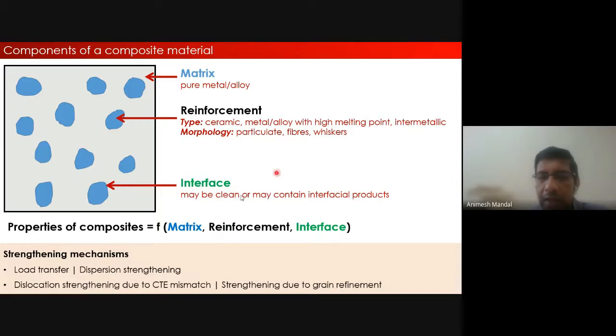So the interface plays a very, very important role apart from the matrix and the reinforcement. What we can summarize is that the properties of these composites are a strong function of not only the major phase and the minor phase, that is the reinforcement, but the interface also plays a very important role in dictating the properties. If you are aware of the several strengthening mechanisms which we cover in a typical metallurgy course: the load transfer mechanism, the dispersion strengthening mechanism, dislocation strengthening due to coefficient of thermal expansion mismatch, or strengthening due to grain refinement. There are a few more, but these are some of the important strengthening mechanisms. They can be influenced by the interface, because if the interface is weak, all of these could be affected severely. That's the reason characterizing the interface in a metal matrix composite is very, very important.